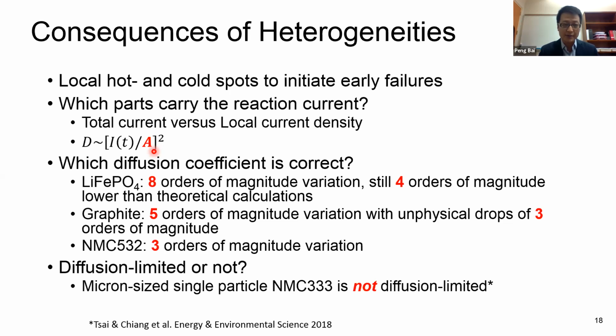You optimize your battery. If it is diffusion limited, okay, you reduce the size of particles, right? But if it's reaction limited, then you should just create a better surface coating or maximize the most reactive facet of that crystal, right? But it always relies on an accurate determination of the diffusion coefficient, which then relies on the accurate determination of the active area, right? So this is why we are focusing on these heterogeneities.